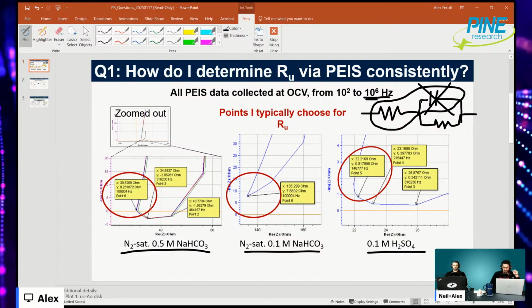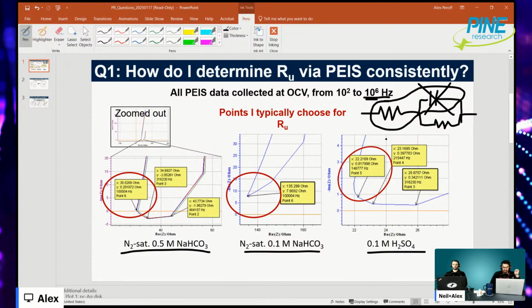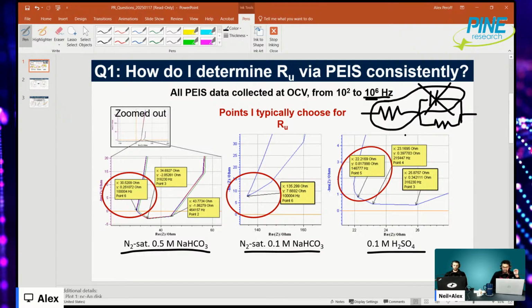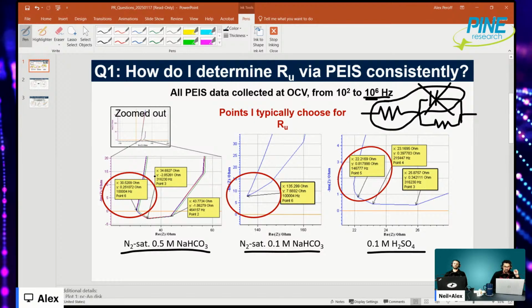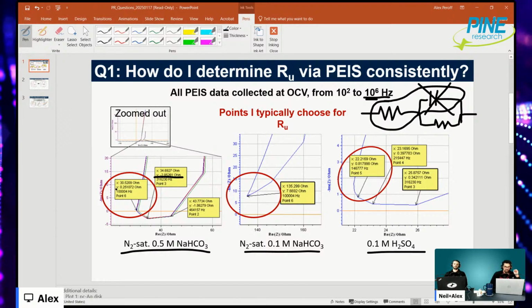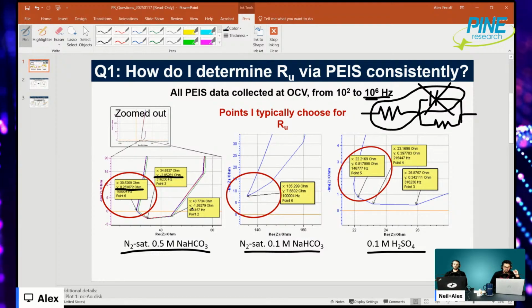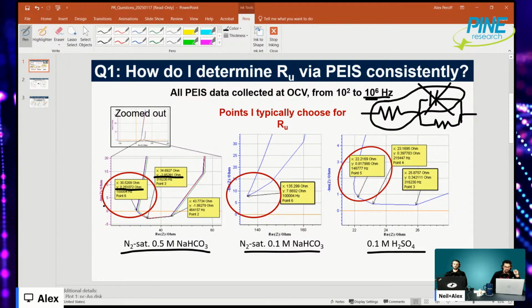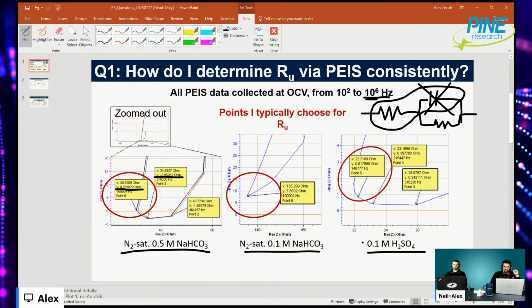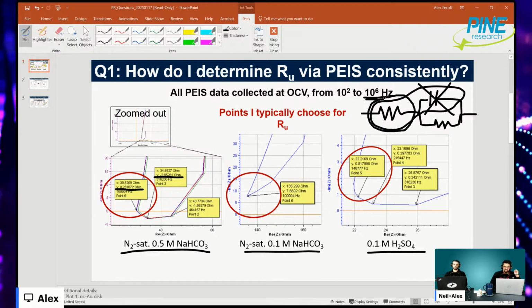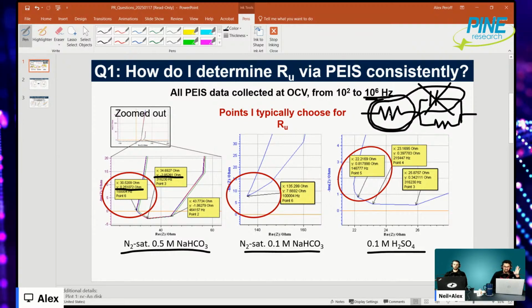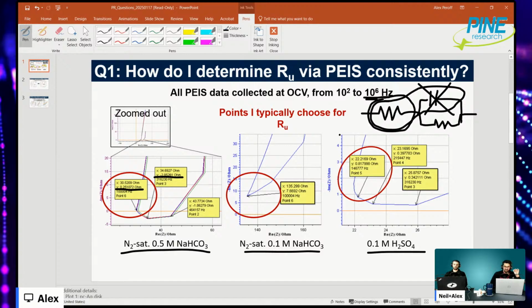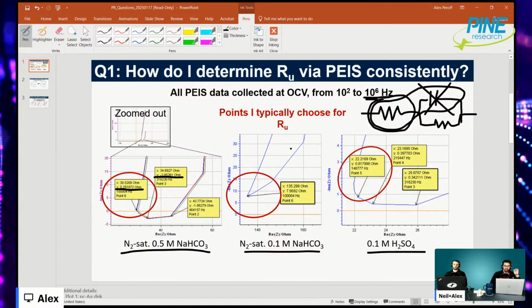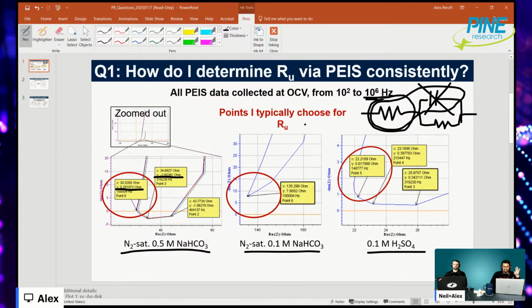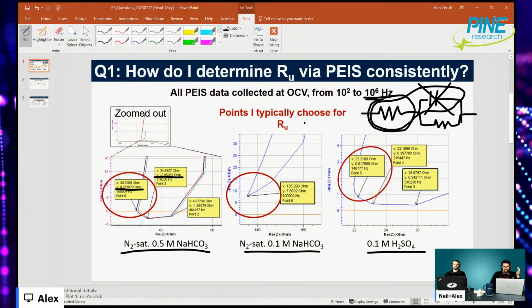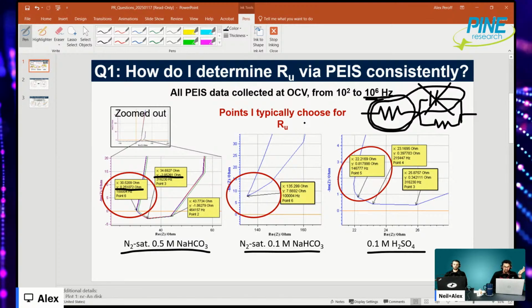So in this view, my thought or recommendation, and Neil, please let me know what you think, is you want to pick the RU where the y-axis value is closest to 0, because any negative imaginary impedance is associated with capacitive values, and the solution resistance, which is ideally the only resistance that you should be getting, should have very little to no phase shift, because an ideal resistor doesn't have a phase shift associated with it. It doesn't have any imaginary impedance.